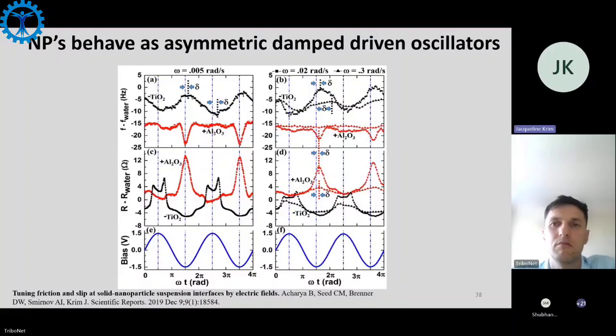there is something that's interesting that pops up at certain frequencies. You'll see the double peak on the titanium oxide that's not present for the alumina oxide. This is the left middle panel as the frequency is changed. And that's showing up at the slower frequencies in the resistance. And that's going to be an important key point to come back to, that double peak. Let's move forward to the next slide.